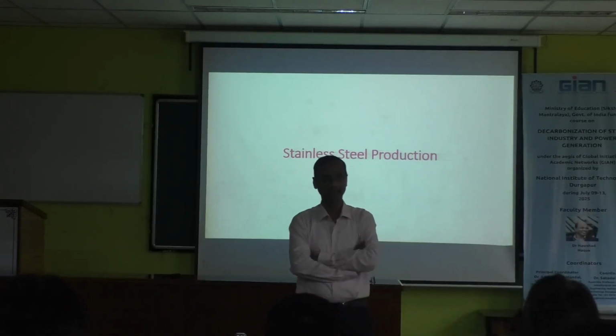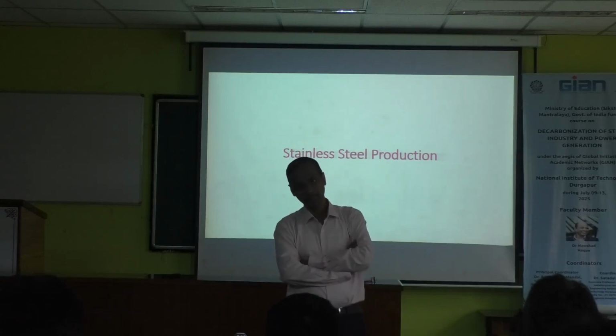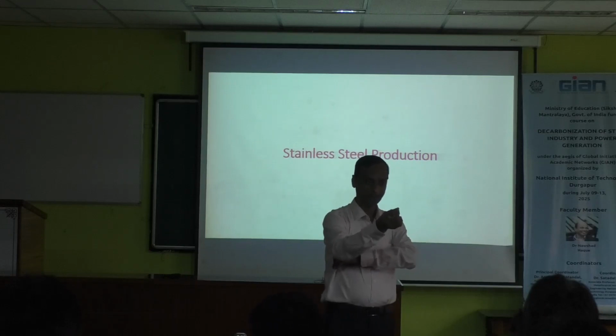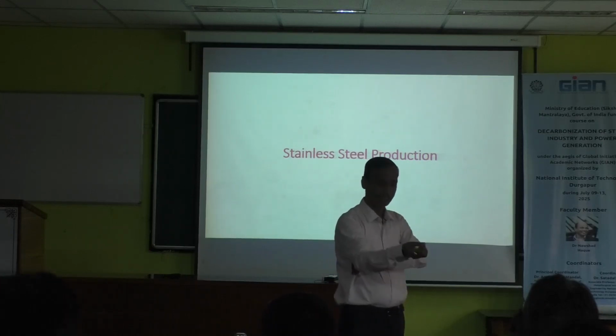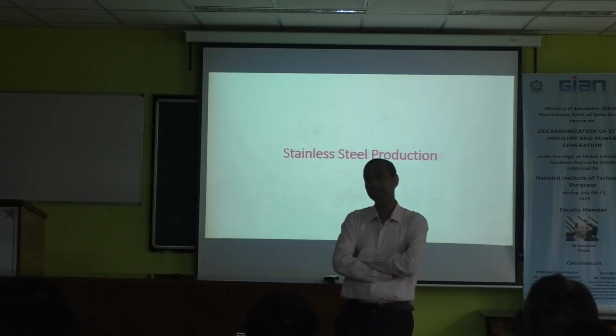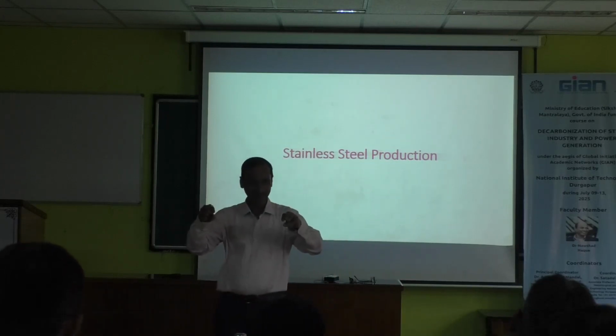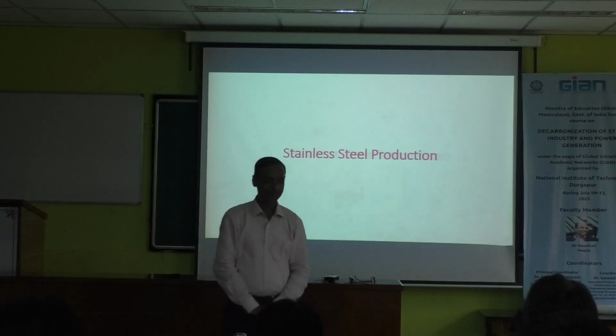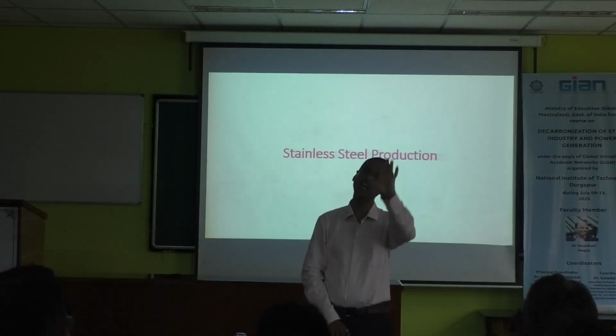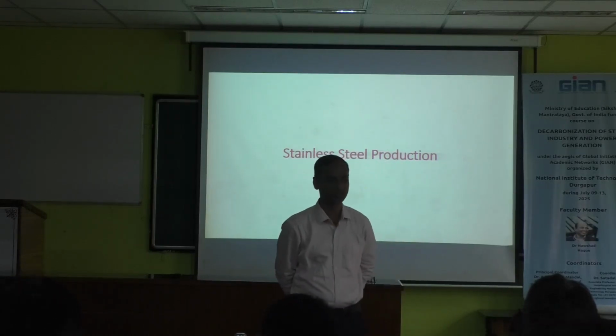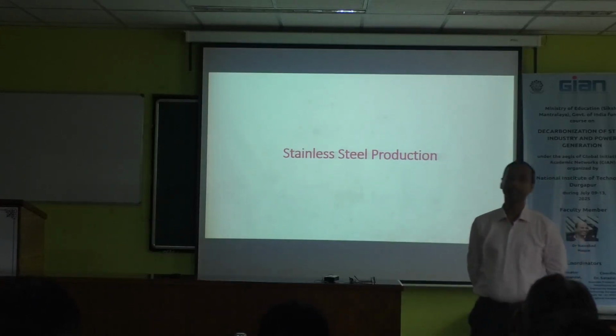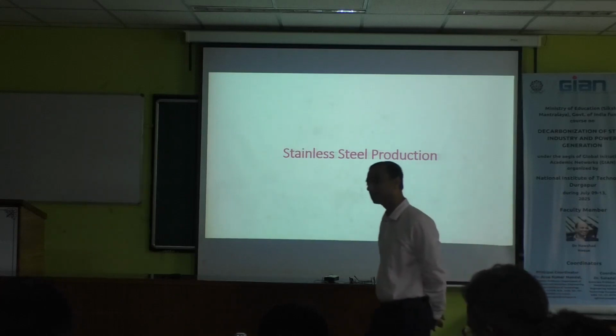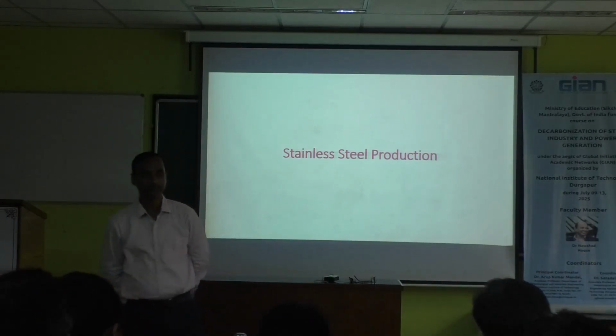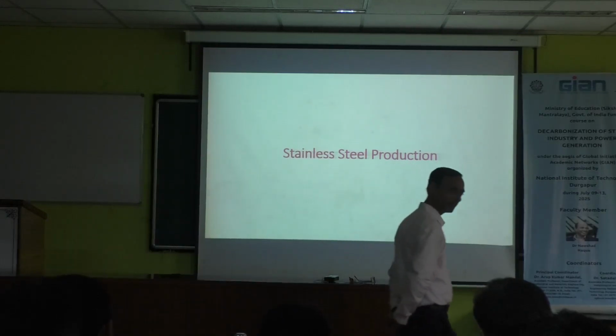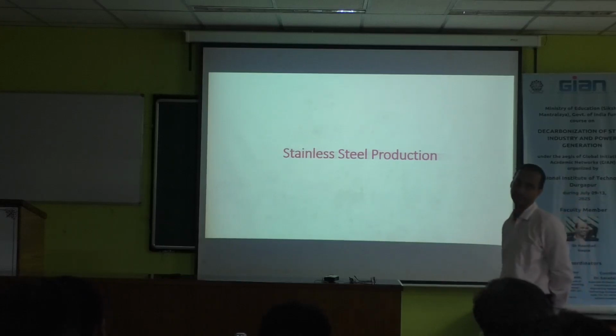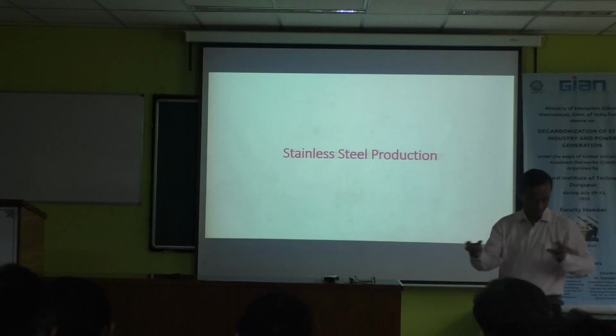You will get an alloy which contains chromium, manganese, and your requirement will be, in place of nickel, nitrogen. Sorry, nitrogen. Then suppose you make these materials in a plasma furnace. Because Cr2O3 has a higher melting temperature, it will not react easily with the carbonaceous materials. High temperature provided by the plasma will accelerate the reduction of Cr2O3. Manganese oxide will reduce to manganese, and it will form a chromium, manganese, iron alloy. As per your requirement, you have to adjust the composition.